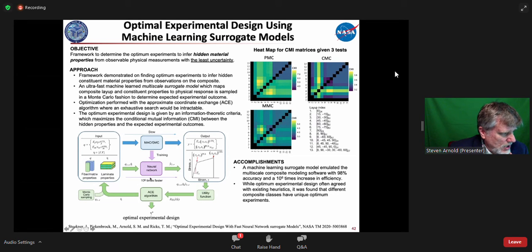But this allowed us then to hook this up to an optimization algorithm, which involved the approximate coordinate exchange algorithm and Monte Carlo sampling to give us the optimum experiment that would provide us with the knowledge about the hidden material properties with the least amount of uncertainty. And here we're showing the heat maps for the conditional mutual information matrix, for 3 different classes of composites, PMC, CMC, and MMC. Basically, what you're seeing is that the specific laminate layup that would give you the best result is different depending upon the system, as one might expect.